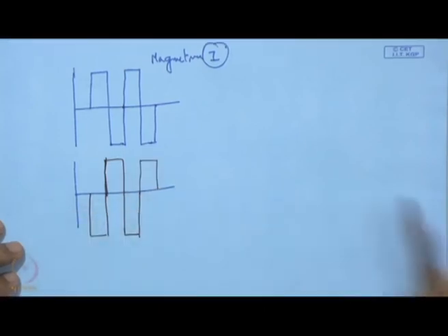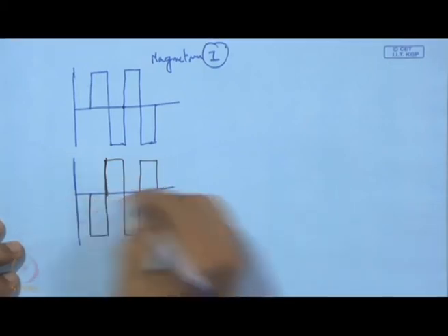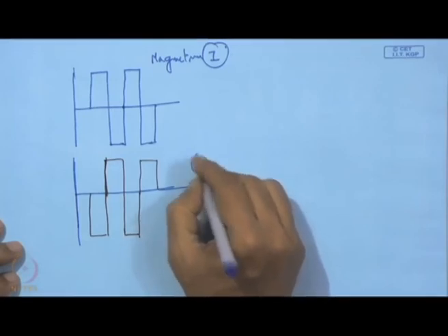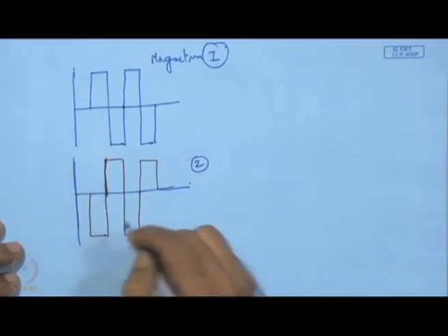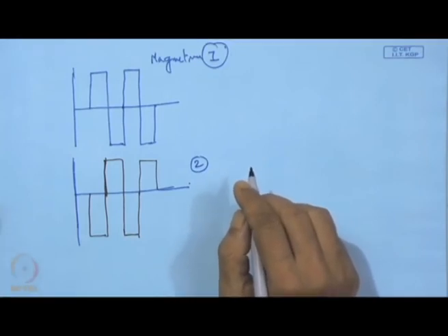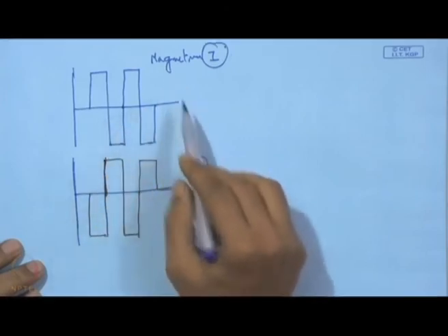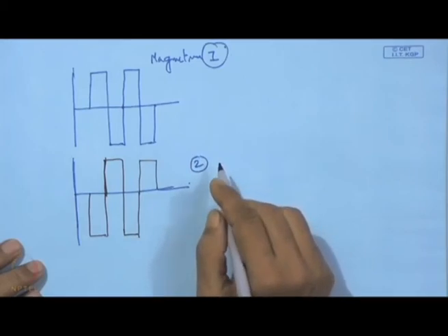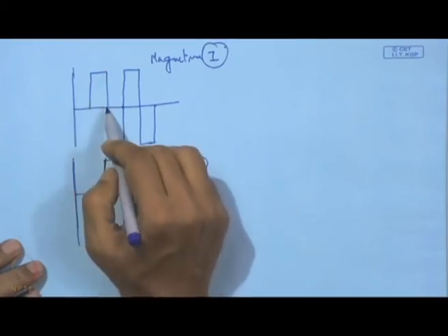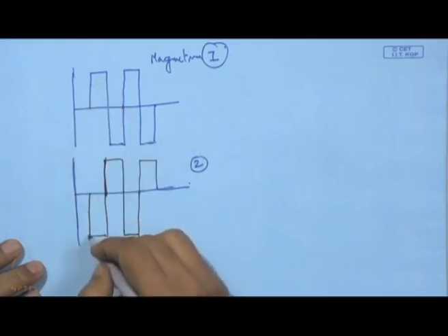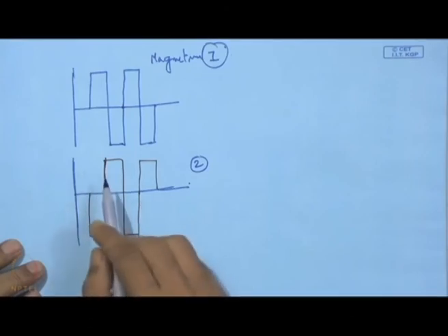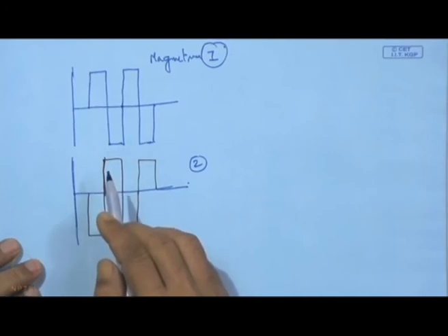What is the advantage in this case? So, what we see is one pulse generator. We must have the pulse generator, and this pulse generator has to be coupled, but in this case just one pulse generator can be coupled with two targets, like twin targets, and when one is under positive polarization, the other one will be with negative polarization, and this way one power supply can be well utilized.